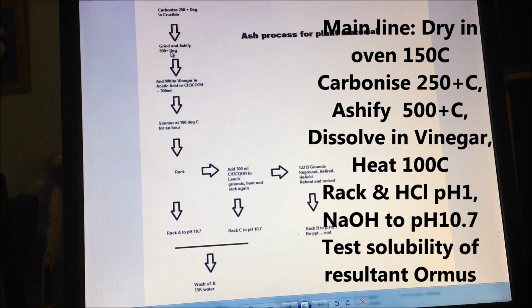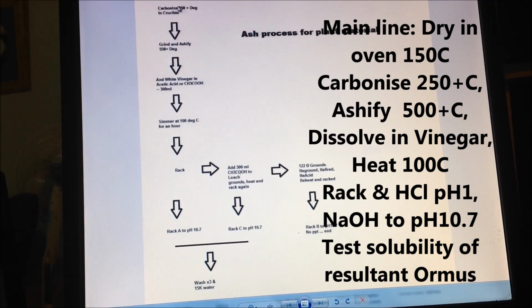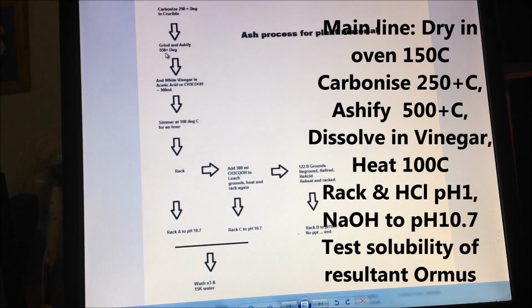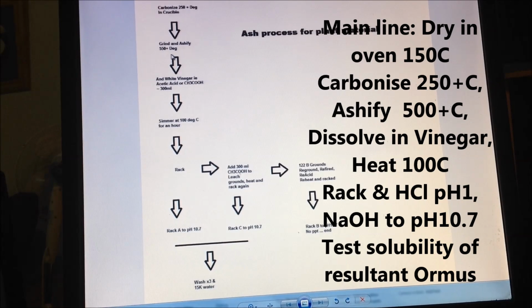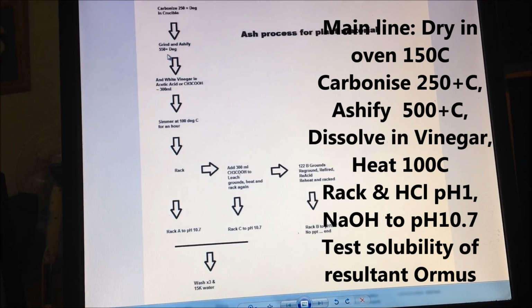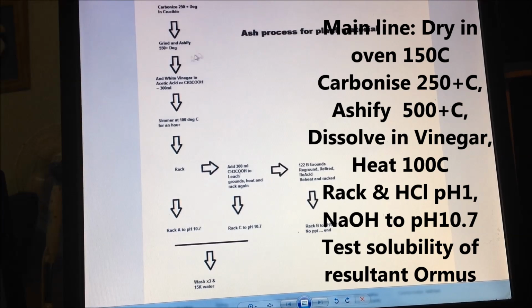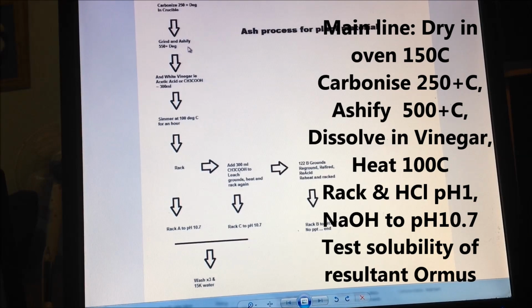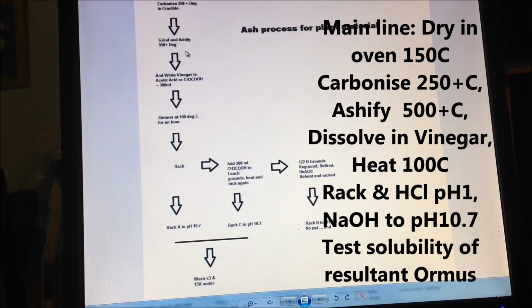So it will smoke again at the start, so you're starting off from a similar sort of temperature, and just as it tolerates it, you gradually increase the flame without producing too much smoke. In the end you'll find that the bottom of the container will start to glow a little bit, and from my metallurgical background you'll be above 600 degrees when that happens, but your ash won't necessarily be at that temperature because it radiates heat pretty quickly, and you've got to transfer the heat from the container to your ash. Anyway, you keep the heat on it and keep stirring it every 15 minutes to half an hour.